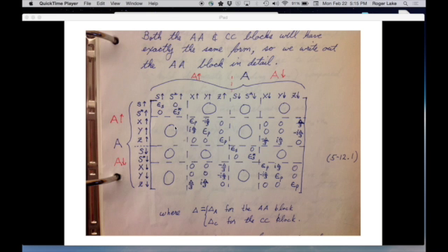Down the diagonal, if you just look at the diagonal elements, that's what we had before, this epsilon s. Well, I guess I wrote it here with an S star, which we haven't talked about. So you'll see this, and I think I'm going to do this in the last homework assignment, have you actually calculate the band structure of, I haven't decided, probably silicon. And to get that X value right, you need this extra S star state. What it represents is an excited S state.